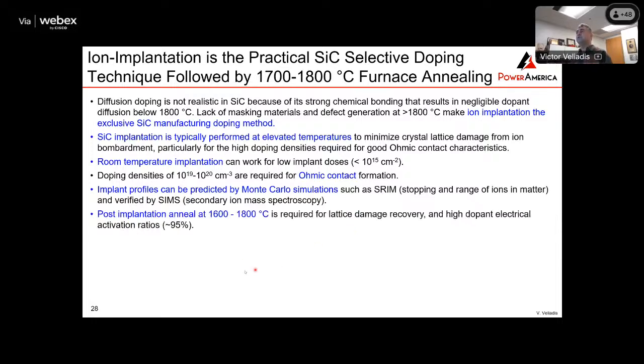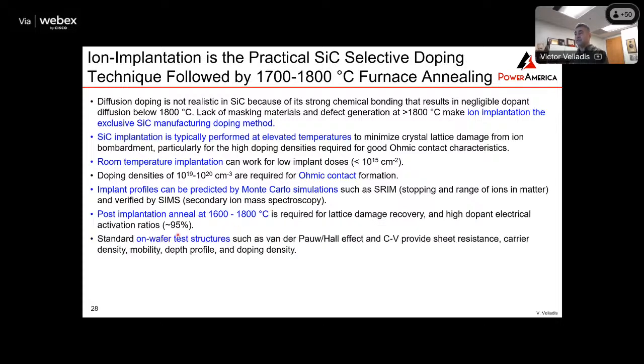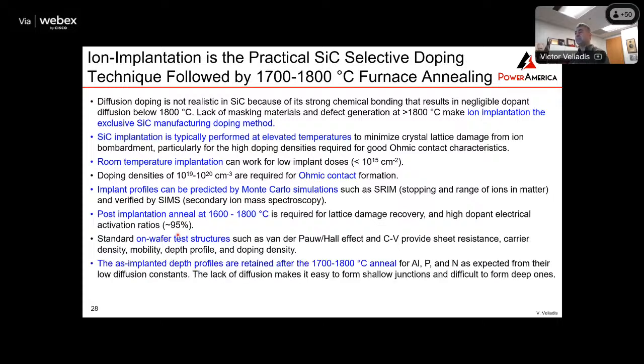And after you're done with the implantation, the wafer basically has lost its crystallinity, and you also need to activate the implant species, the dopants. So you need to do an anneal, typically done at 1,700 to 1,800 degrees, in order to get the activation and recrystallize the wafer. And you can put test structures to basically measure different aspects of your implantation and improve the process. And the implanted profiles are retained when you do that 1,700 to 1,800 degree anneal, because as I mentioned before, there's very low diffusion in silicon carbide unless you go to extremely high temperatures.